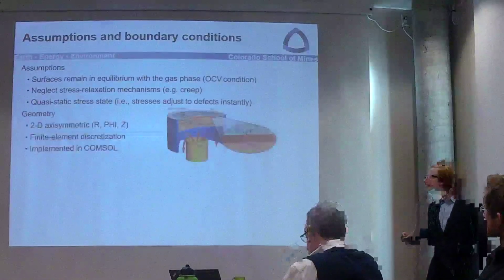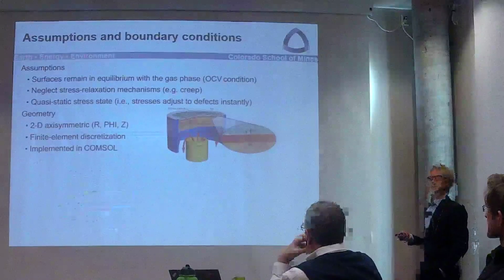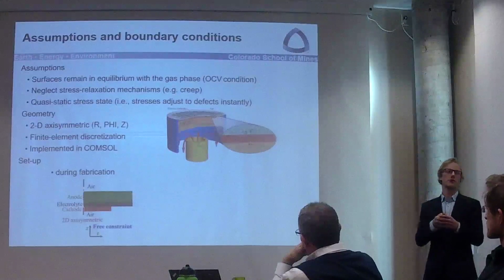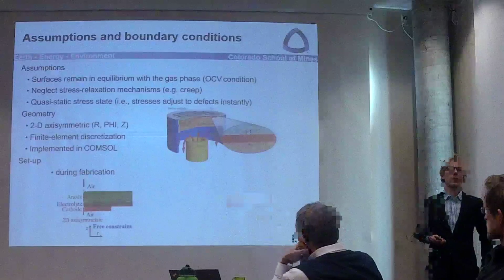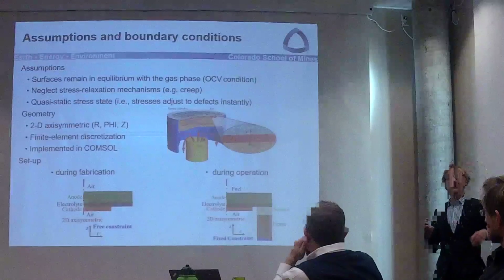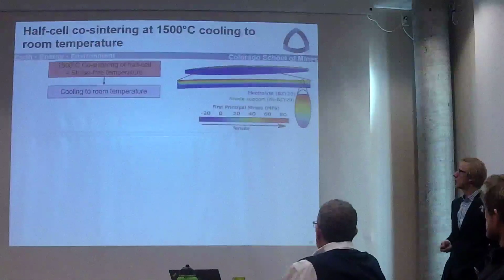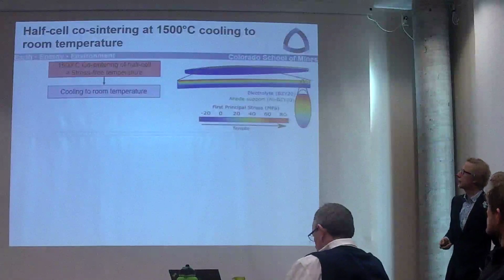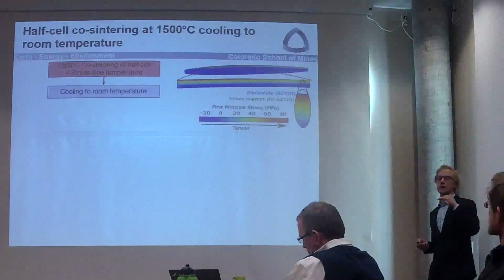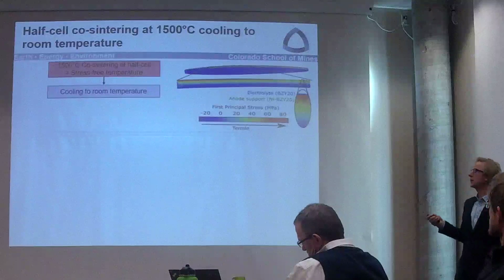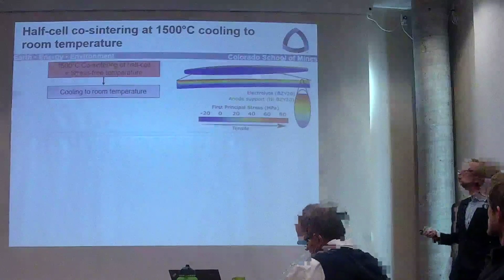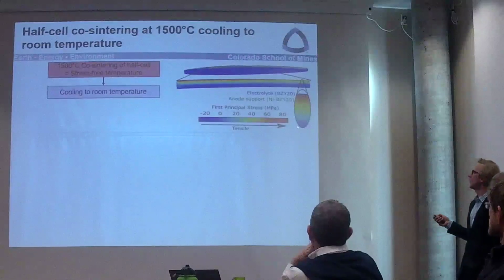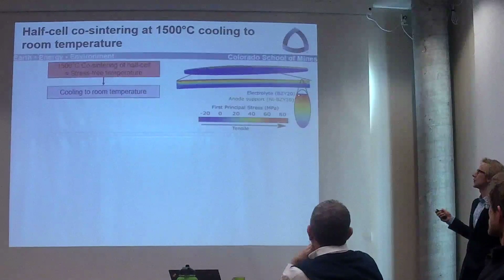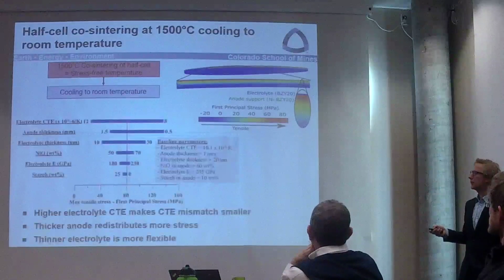We have a sealant. In fabrication, we assume that the cell is free to move at the bottom. And so that way we're trying to match with experimental data. So when we look at this little cookie here, which is the anode and the electrolyte, and then we cool it down, we get to 80 megapascal. And that 80 megapascal is here really at the interface between the anode and the electrolyte.